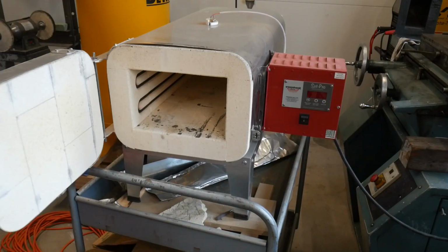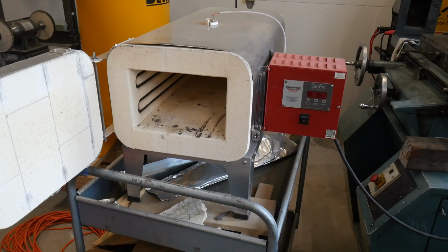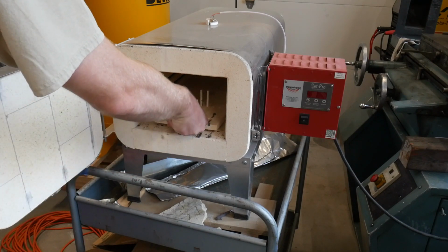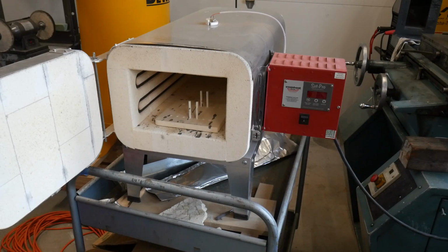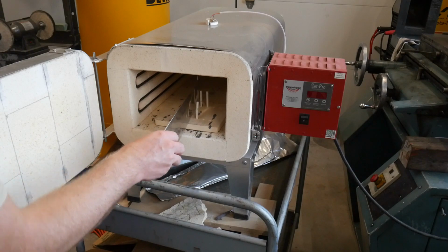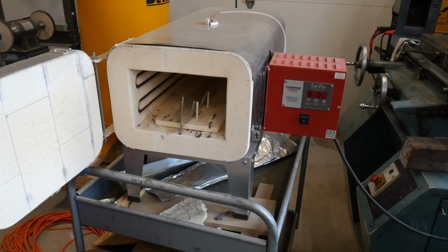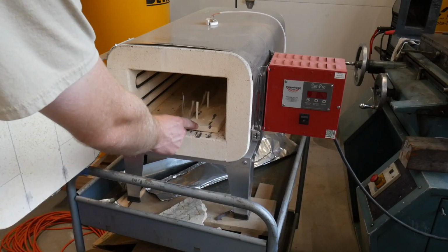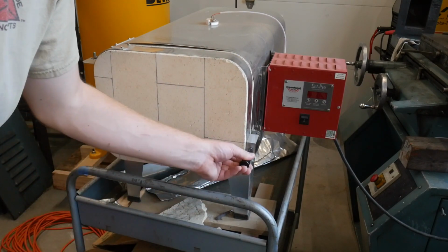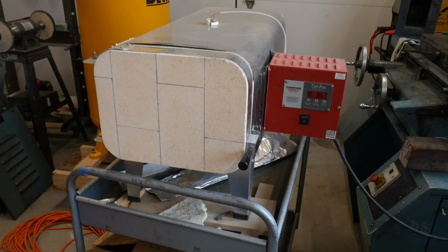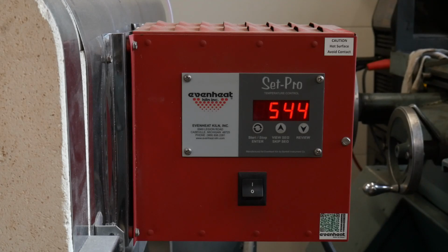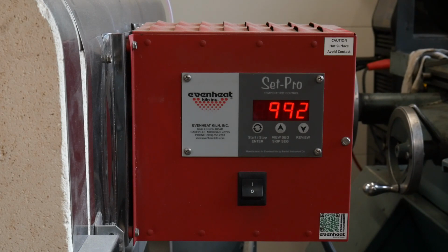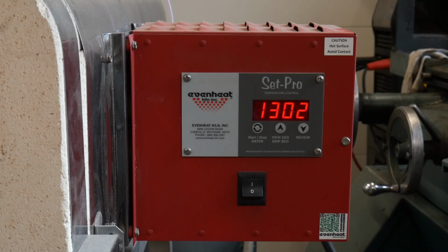With the package ready, I can now set up my heat treat oven. This knife is made out of CPM S30V steel, so we're going to take it up to 1600 degrees Fahrenheit and preheat it for 30 minutes, and then take it up to 2000 degrees Fahrenheit and oil quench it. After that's done, we're going to temper it twice at 400 degrees Fahrenheit both times.